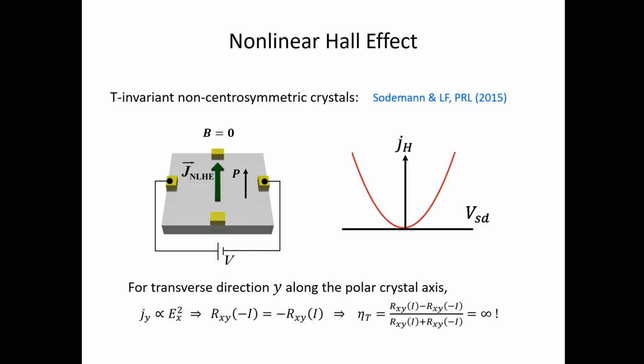So all these cases are the linear response Hall effect, and they all require time reversal breaking. And we started, together with Sodemann, who was a Pappalardo fellow at that time at MIT, to explore the possibility of a Hall effect in the nonlinear regime preserving time reversal symmetry. So again, if we take a time reversal invariant material, at the level of linear response, the Rxy has to be 0. However, if we go beyond the linear response regime, we found that a quadratic current-voltage relation is allowed. And this means that if we pass a current in the x direction or apply a voltage in the x direction, we can get a transverse current in the y direction if the material has a polar axis, okay, along the polar axis direction. There could be a quadratic Hall current.